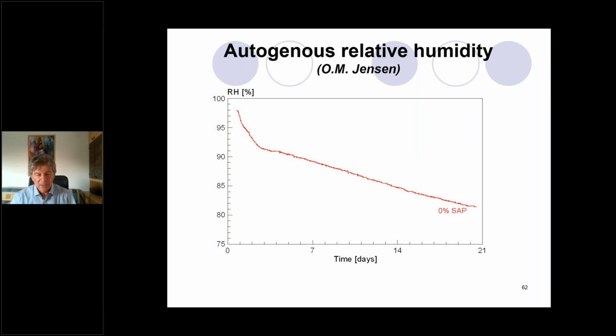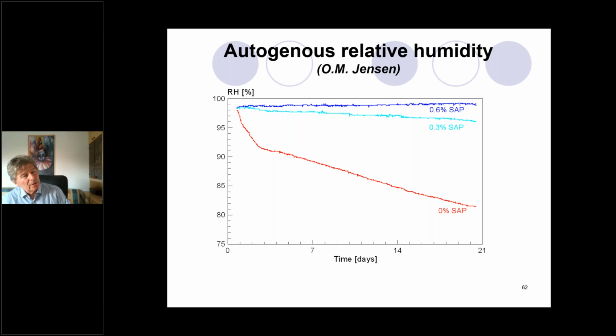Relative humidity, again, this is zero content of SAP. Everything is calculated relative to the cement content. When we add just 0.3% of superabsorbent polymer, we almost succeed in compensating autogeneous shrinkage. If we put a little bit more, 0.6%, we have a completely compensated situation. But of course, polymers cost money. So in comparison with lightweight aggregates, this technology is more costly. But it depends on the situation on the market, and more superabsorbent polymers are now generated and developed in the world, and the price for 1 kilogram of superabsorbent polymer has been reduced dramatically during the last 5 years.